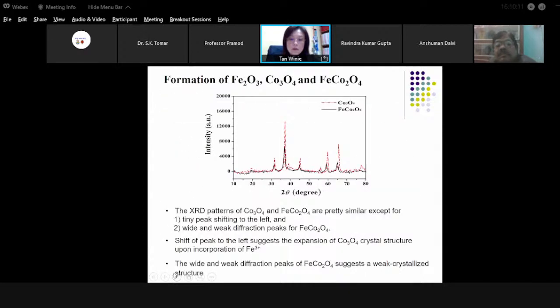Okay, so you can see that there is a tiny peak shifting to the left, and also wide and weak diffraction peaks for the iron cobaltite. The shift of the peak to the left suggests the expansion of the cobalt oxide crystal structure upon incorporation of the ferric ions. The expansion of this crystal structure is important because it leads to the expansion of channels, which will be beneficial for the transport of ions and also electrons.